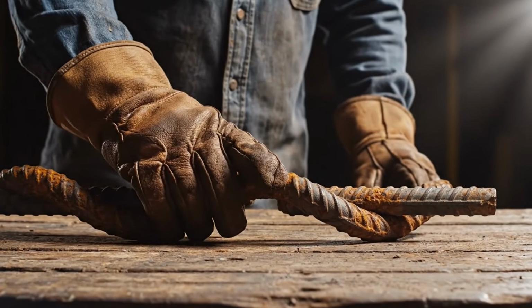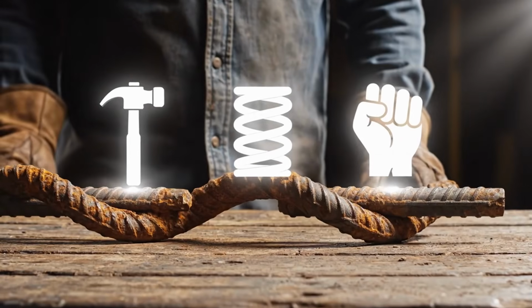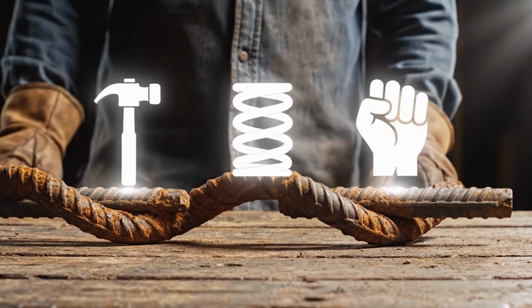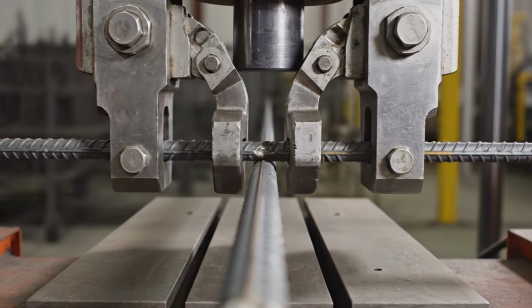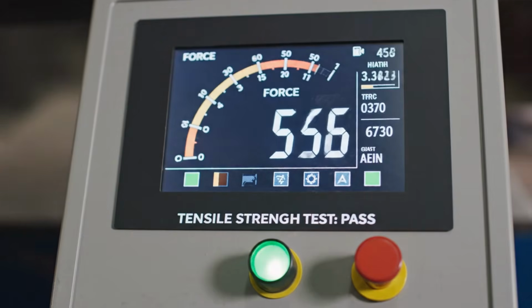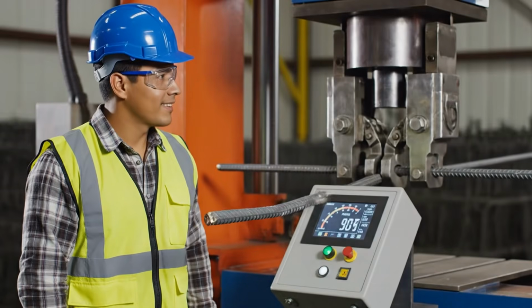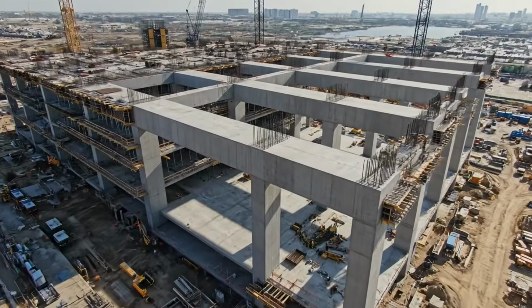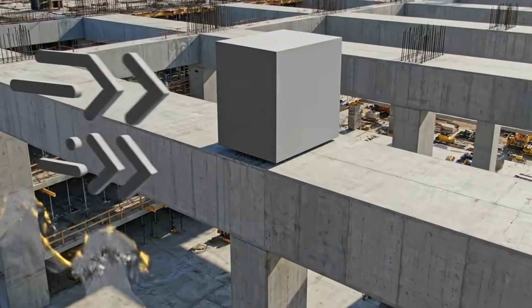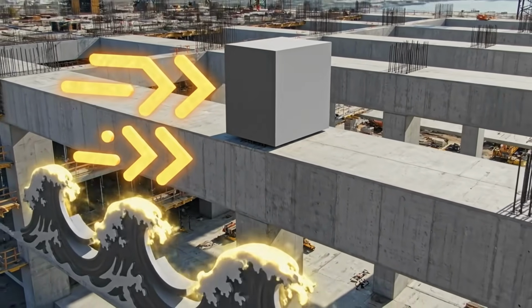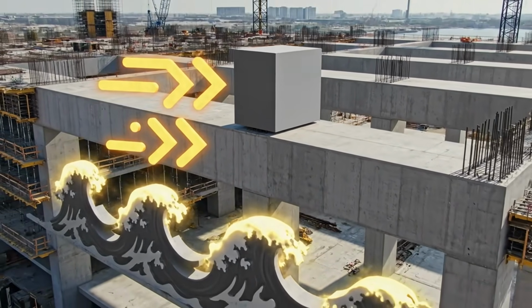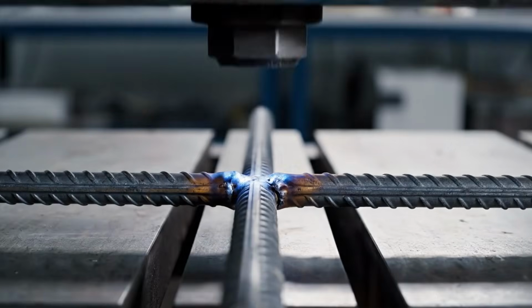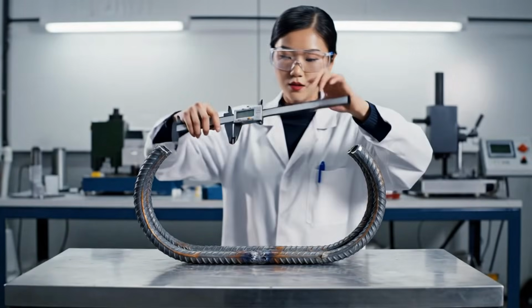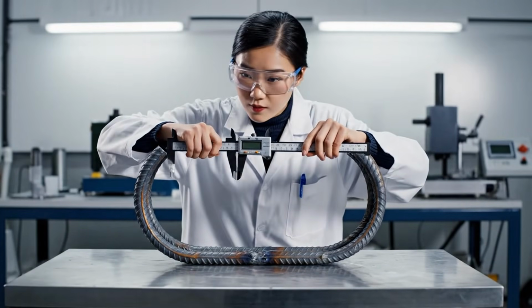After corrugating, many plants apply accelerated cooling using water boxes or similar systems. This step not only lowers the temperature, it also acts as an inline heat treatment. The surface cools rapidly and the core remains hotter for a brief interval. Then, the internal heat migrates outward and metallurgical transformations occur that increase the mechanical resistance of the bar without making it excessively brittle. This balance is essential.